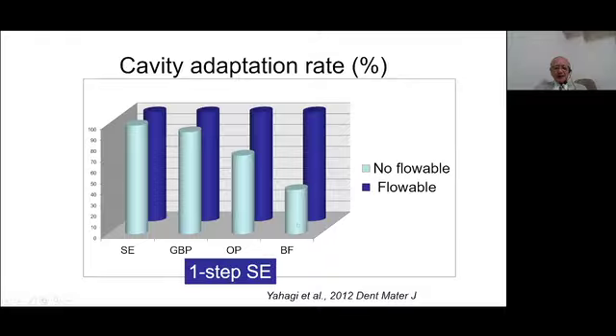In the one-step self-etching adhesive, some gaps, some debonding was observed with the one-step materials when we did not apply the lining. But when we apply the flowable composite lining, even with the one-step self-etching adhesive, there was no gap. Perfect adaptation was observed. However, in the case of two-step self-etching, even without the flowable composite lining, the bonding was very excellent. No gap observed.